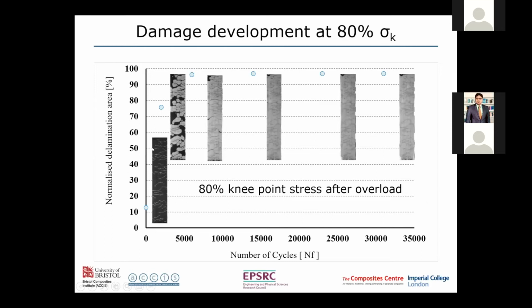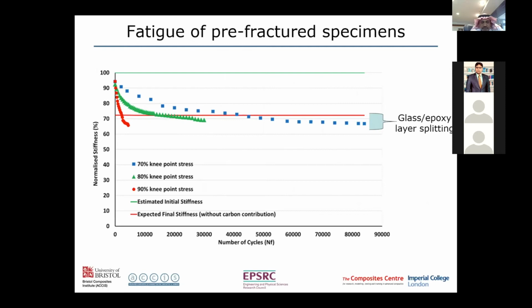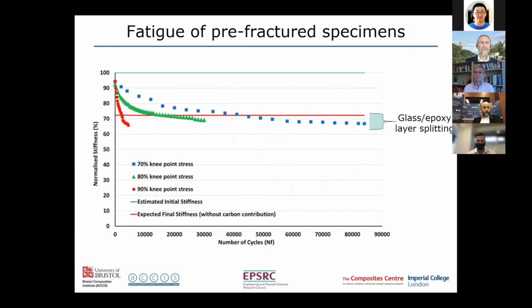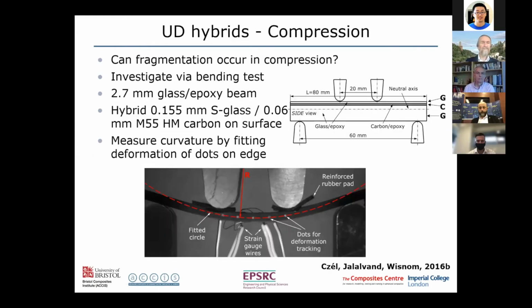Then we start to get propagation. And eventually the whole specimen delaminates, but it's still able to carry load because the glass is intact. And if you look at the different levels here, plotting 70, 80 or 90% of the knee point stress, you can see that at 90% of that knee point stress, it delaminates after a few thousand cycles, but at 70% it goes for a few tens of thousands of cycles before it delaminates. So overall, this fatigue performance looks quite good.